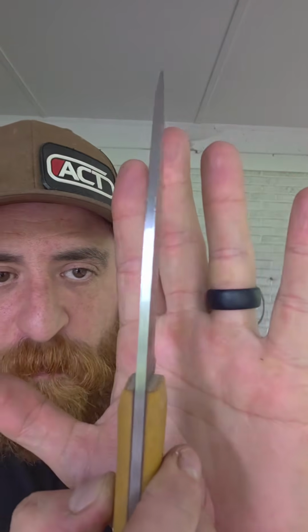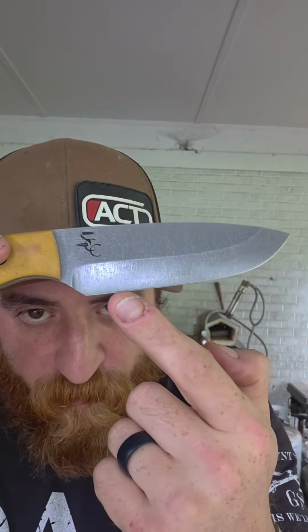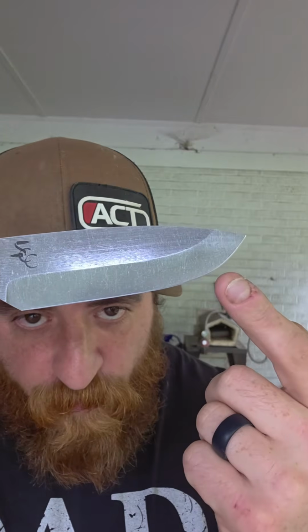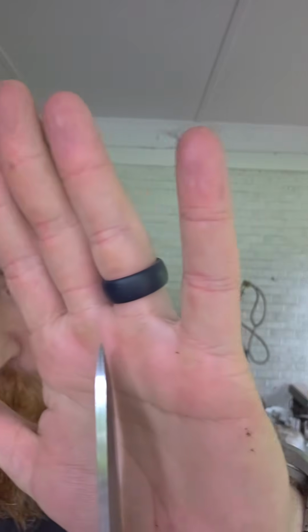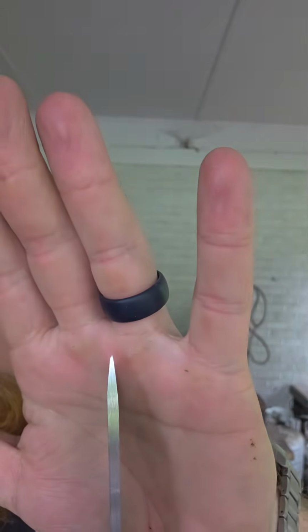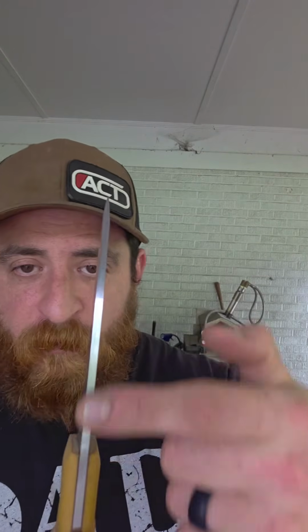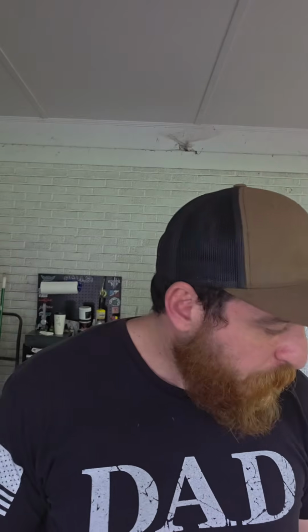So we're about 130 thousandths at the spine. It's about 20 thousandths behind the edge right here through here, and then up here at the tip is about 25. It's a little thicker. Robust tip, because we all like a thick tip. Am I right, ladies? I 90 degreed the spine because some guys want that, and the other ones I was leaving tumbled. But you don't need a 90 degree spine to throw sparks. I don't know why the bushcraft community hasn't figured that out yet, but they prefer it that way, so that's fine. So I just make it nice and shiny so you can throw sparks with it.